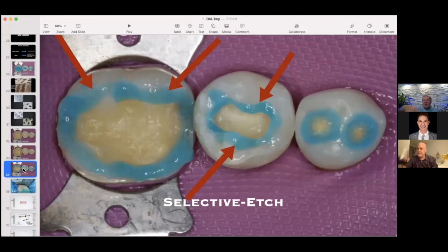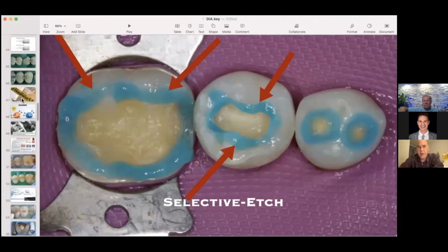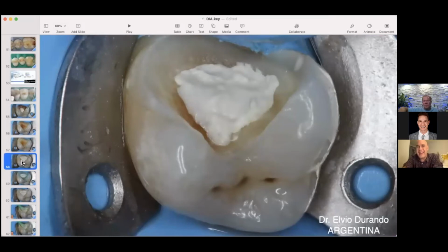So let me ask you another question. There's adhesive and cohesive failure. If you put too thick a layer, and let's go to Theracal just because you're most familiar with it, if you saw a bond failure, you're going to see cohesive failure within the Theracal? Yeah, because, specifically talking about Theracal, that guy is super opaque. So when you use Theracal in a thick layer, your light is not going to be able to cure the deepest part of that layer, because it's not going to go through. And this is because of the calcium that is part of the formula. So you're going to have cohesive failure and you're going to have problems. You might even see a flaking off of the Theracal because it didn't cure.